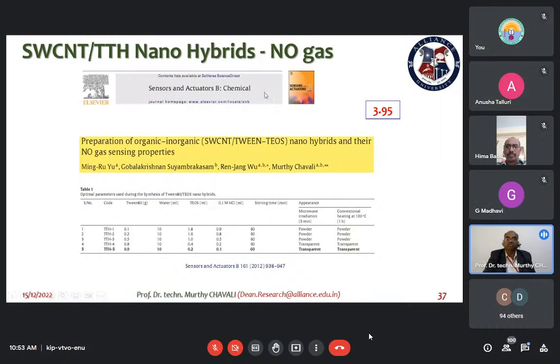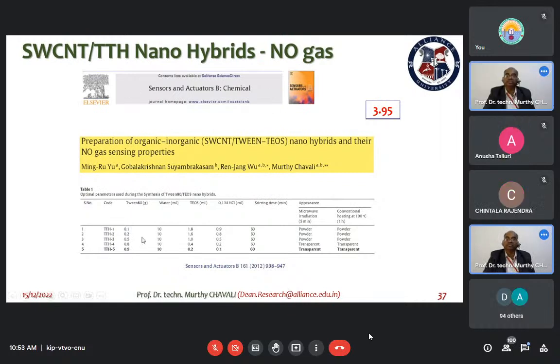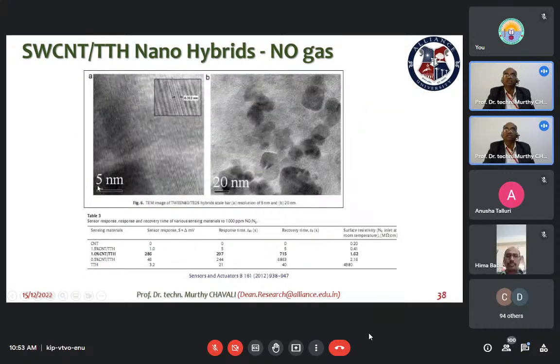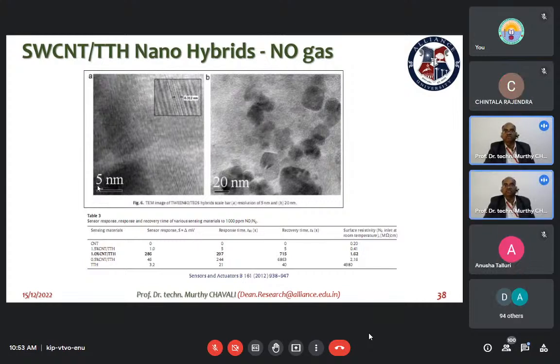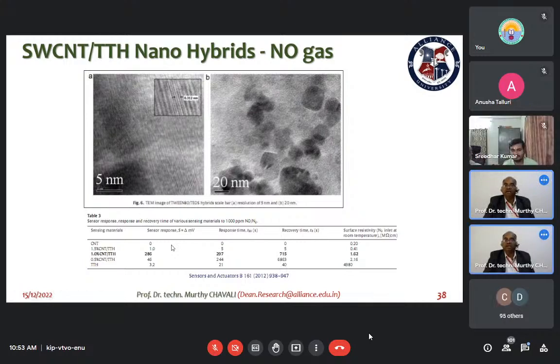But the beauty of this is we can prepare these in a laboratory scale microwave method in almost 1 to 2 minutes. And once we prepare different combinations of different concentrations, we were able to test this over a period of 1 week. And then we have found out that these hybrids, incorporating the properties of organics and inorganics put together, were able to detect something very less than 100 ppb.